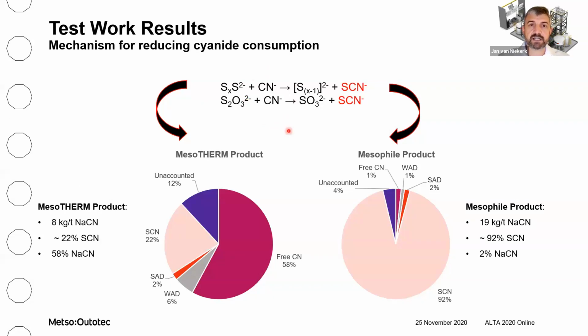If we look at a typical Fairview ore sample that we treated using mesophile and then mesotherm, for the mesophile product to achieve good gold recovery, we required 19 kilogram per ton cyanide addition, with about 92% of the cyanide lost to the formation of thiocyanate and only a very small amount of cyanide still available for leaching at the end of the test.